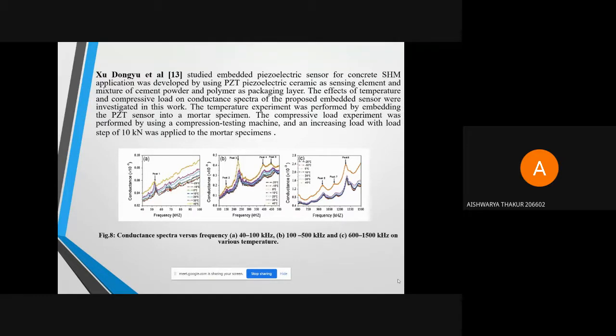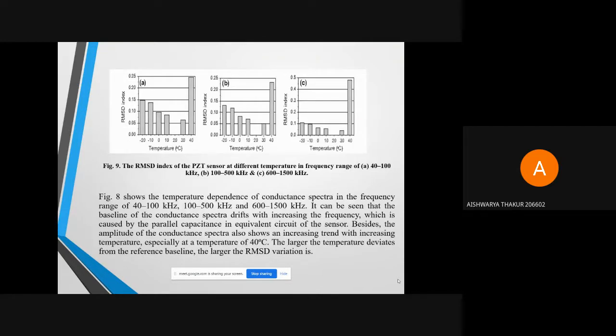The RMSD index of a piezoelectric sensor at external load at selected frequency were observed, and it was found that RMSD index in conductance spectra differ with increase in frequency, which is caused by the parallel capacitance in the equivalent circuit of the sensor.